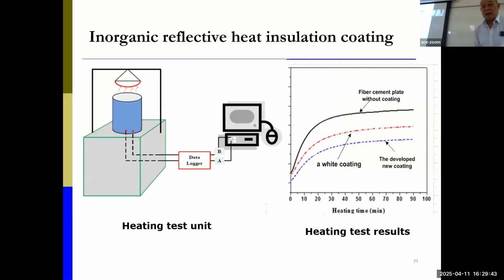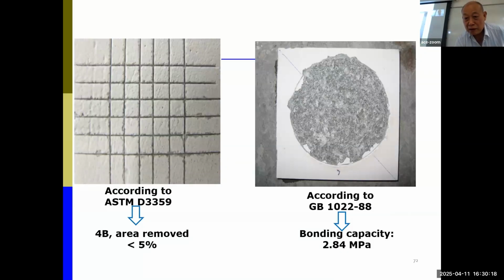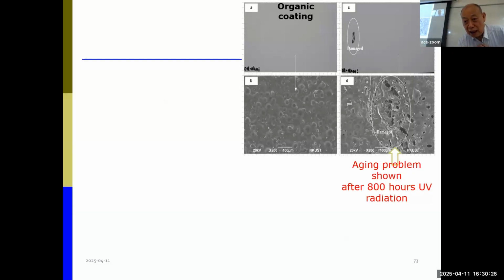You see the improvement. And then we utilize another testing method, also using infrared, and on the box top we have a hole. With the plate with and without the coating, we measure the temperature at the bottom side. Here the black is without coating, the red one is the commercial coating, and the blue one is the coating we developed. It showed very good, and they showed the bonding between the coating material and the substrate, and we did this UV test. For the organic material, you can see they have very heavy damage after 800 hours UV radiation.